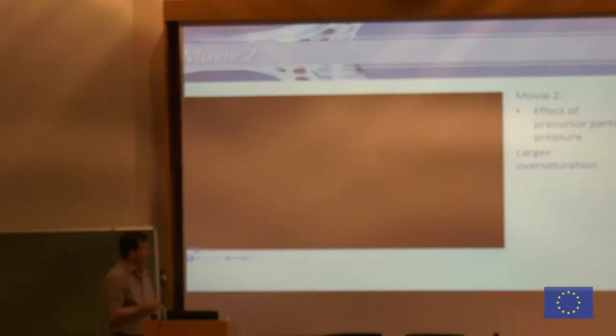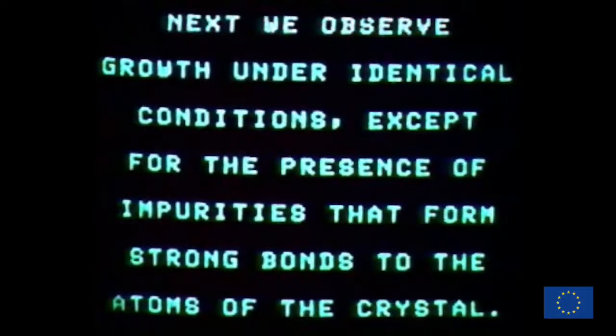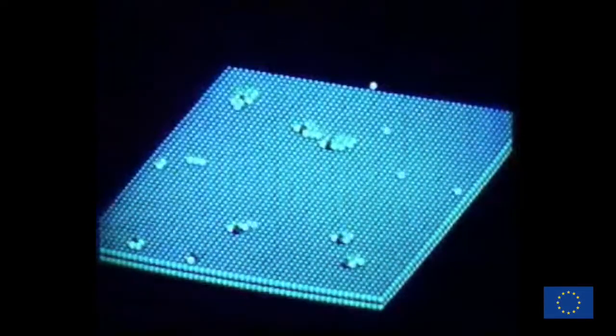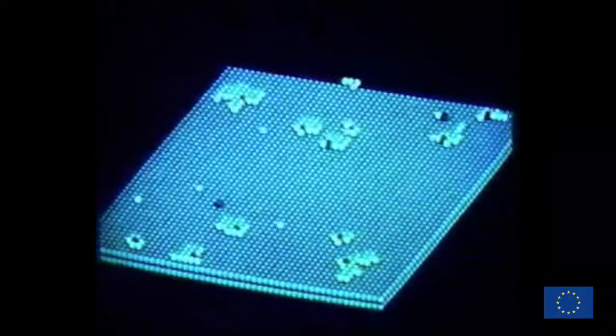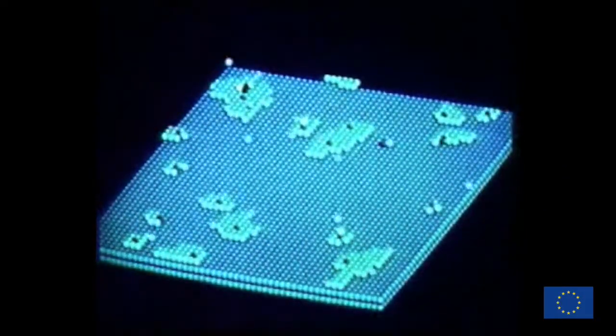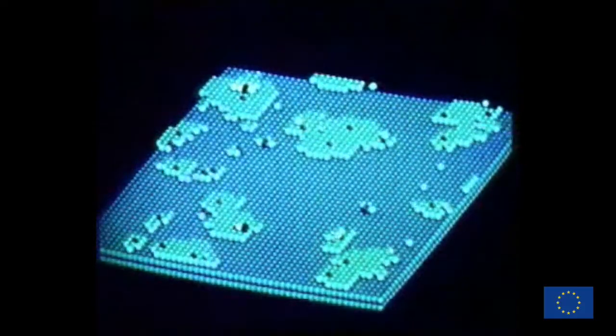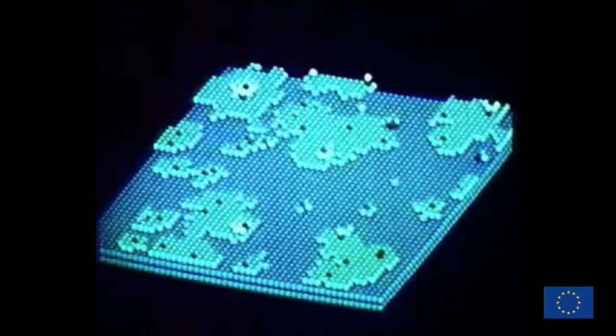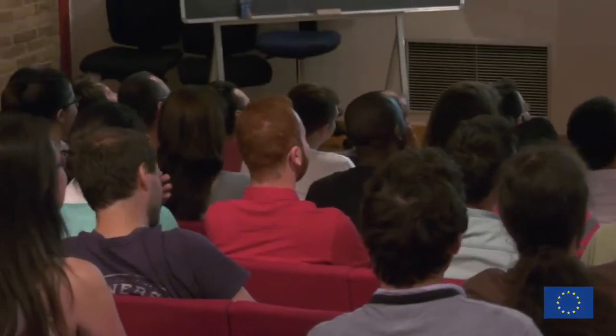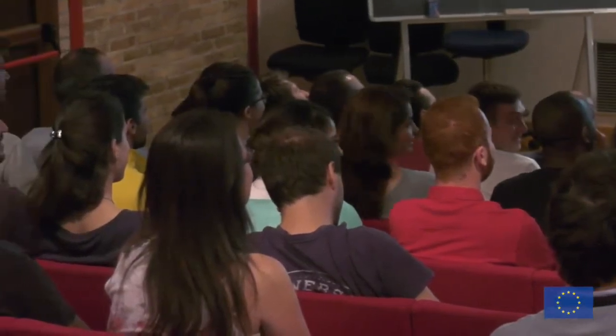The next 2 movies, there will be 2 new concepts that I want to introduce. The first is contamination. Epitaxial growth is very sensitive to contamination, and we will first have a similar movie to what we have seen before. So we have the nucleation, and the black atoms that now appear are contaminants. They are atoms, for instance, oxygen, that very easily bond to all the rest. And you can clearly see that these impurities act as nucleation sites for all these islands. The islands preferentially form around one of these contaminants, which is maybe a little bit misleading because you may think this is a beneficial effect. It will help you for nucleation.